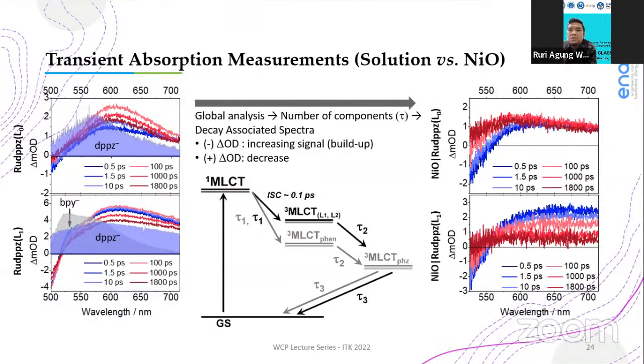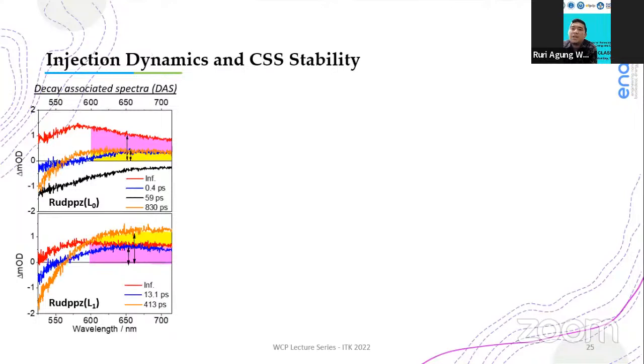So what we do next is to globally fit again the transient absorption data on nickel oxide, and the decay associated spectra are also presented as follows. We have the first decay component, which is characterized by a time constant of a few picoseconds, which shows negative delta OD signals. Even though it is less prominent, this reflects the build-up of oxidized nickel and reduced complex, and therefore it is assigned to the hole injection process.